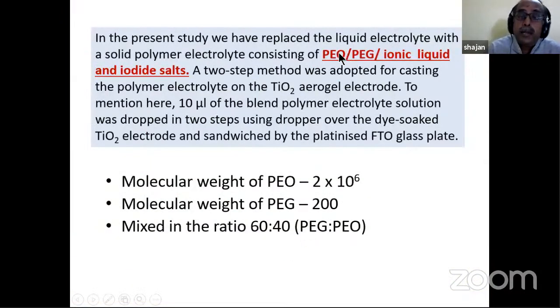And in the polyethylene oxide, there's electrolyte. As I already told you, we have included the iodide salts along with that, so that will be acting as the redox couple for electron transfer. And this polymer is a mixture of polyethylene glycol and polyethylene oxide in the ratio 60:40. The electrolyte is a separate area that I don't want to discuss here now because it's very elaborate.